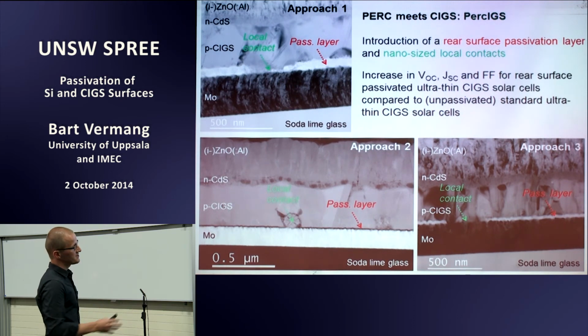But in all 3 cases, we were able to increase VOC because of the passivation effect for very thin cells. At the same moment, we were able to increase JSC because of the reflection of the passivation layer. And we were even able to increase fill factor a lot in the case of the well-controlled grids with E-beam lithography.